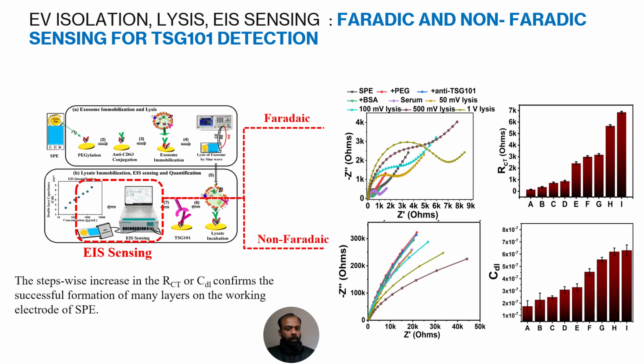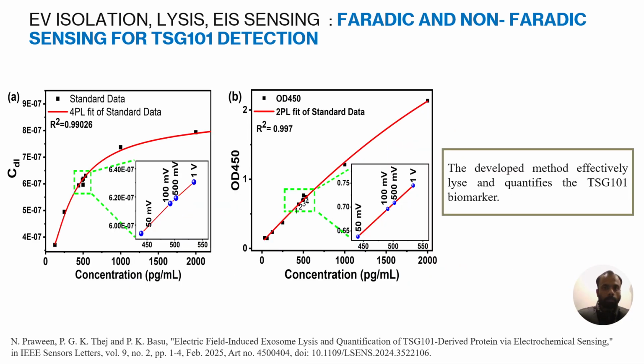The electrochemical impedance technique established for HER2 protein was also extended for studying TSG101 protein. Both Faradaic and Non-Faradaic sensing are studied. At each and every stage of modification of screen printed electrode, we studied either charge transfer resistance or double layer capacitance. The results of the developed EIS system were cross-verified with the standard ELISA technique.